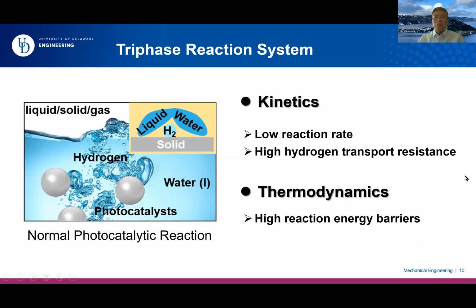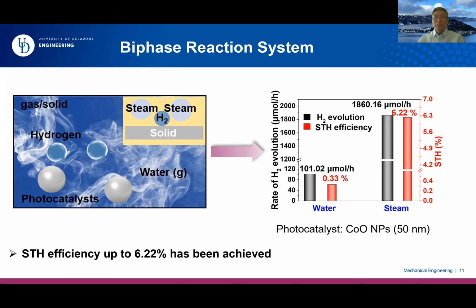The reason is that in the traditional triphase reaction system, from both kinetic and thermodynamic perspectives, there are, for example, a low reaction rate, high hydrogen transport resistance, and also very high reaction energy barriers. In the new system, just by replacing the liquid water with gas water, you can improve the conversion efficiency by 20 times. Just to give you an example here.